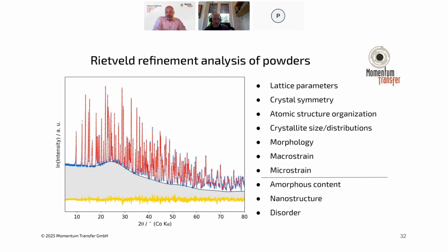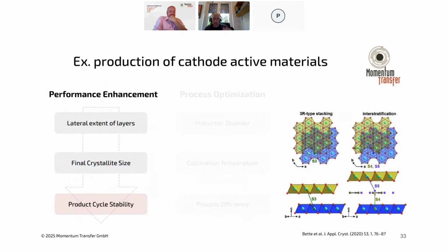Furthermore, you can also indirectly, or in some cases directly, get information about amorphous content. Amorphous materials don't produce sharp diffraction peaks. They produce a broad, diffuse halo of scattering that sits in between and underneath these peaks. This comes from amorphous content, but it can also be affected by nanoparticles, and it can also be affected by disorder in certain phases. And so that can be quantified as well.